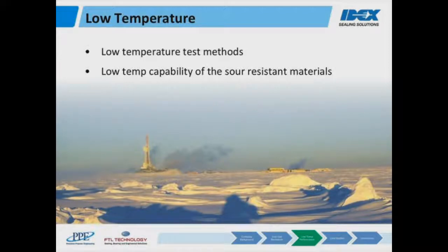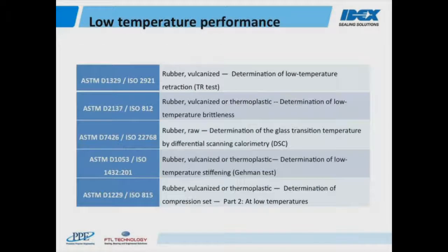They are ASTM D1329, which is the temperature of retraction test, ASTM D2137, which is the determination of low temperature brittleness, ASTM D7426, the determination of the glass transition by DSC, ASTM D1053, which is the Gehman test, and ASTM D1229, which is the determination of compression set at low temperatures. I believe one of the most reliable tests is the determination of the glass transition by DSC, which is the ASTM D7426.